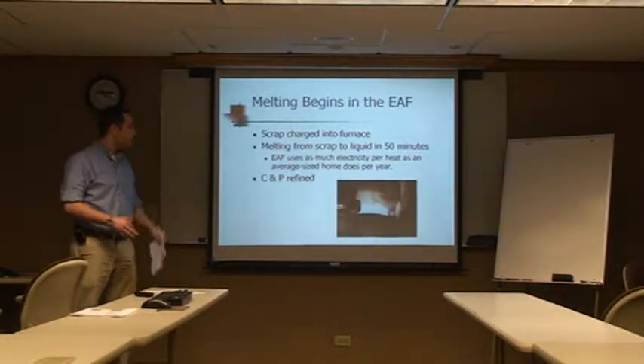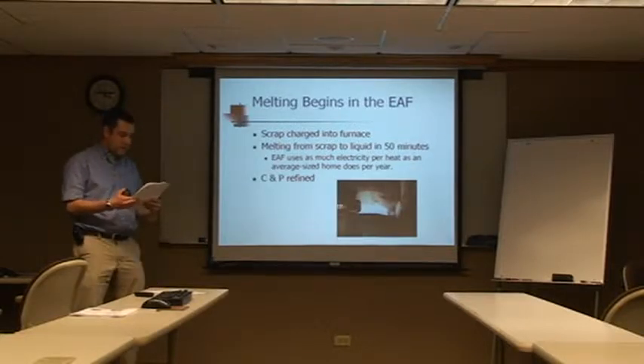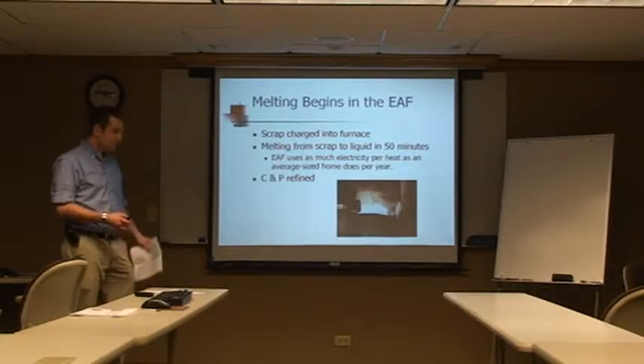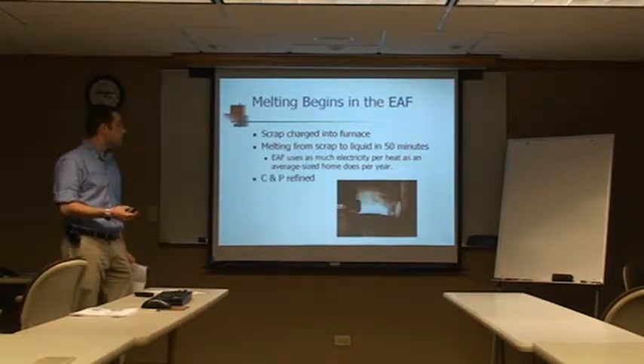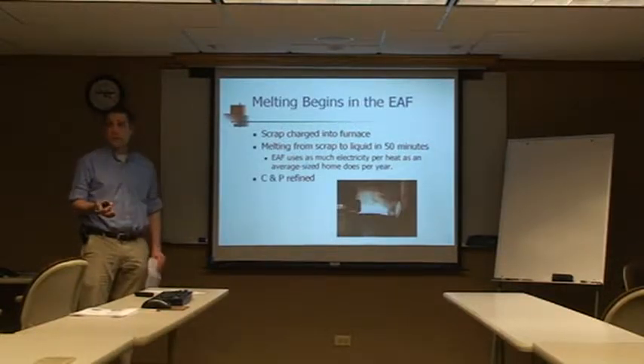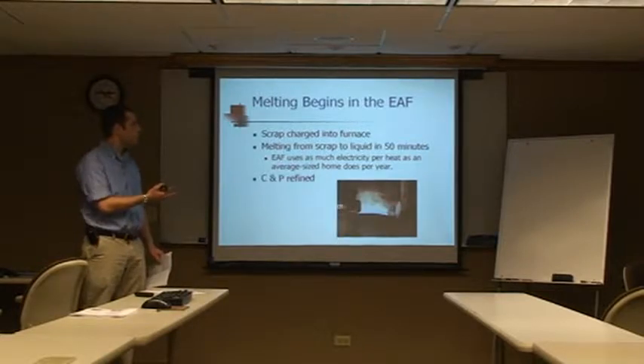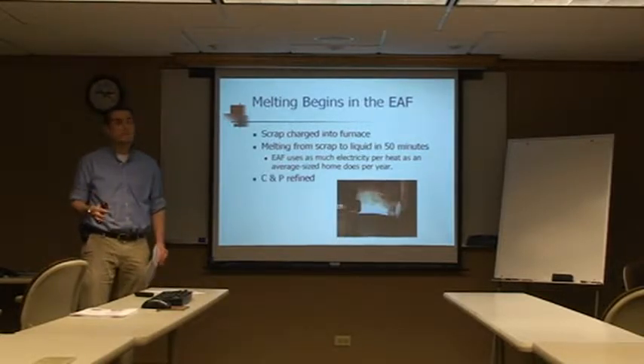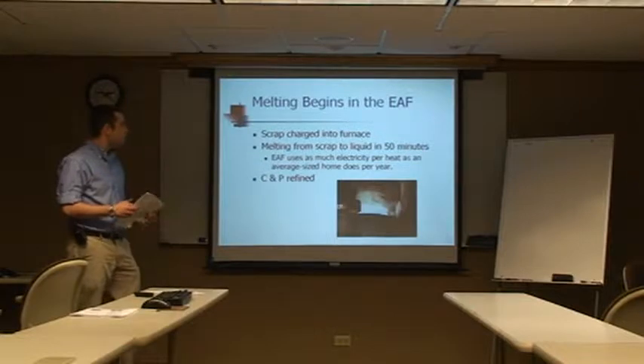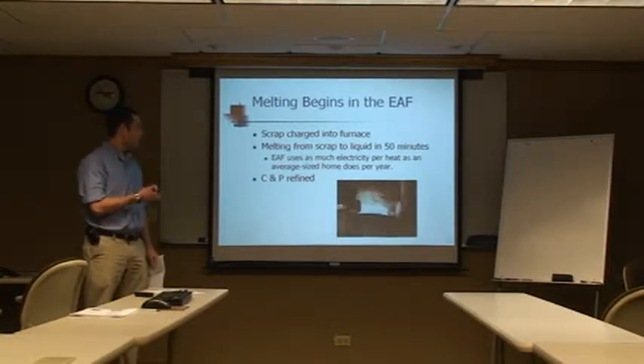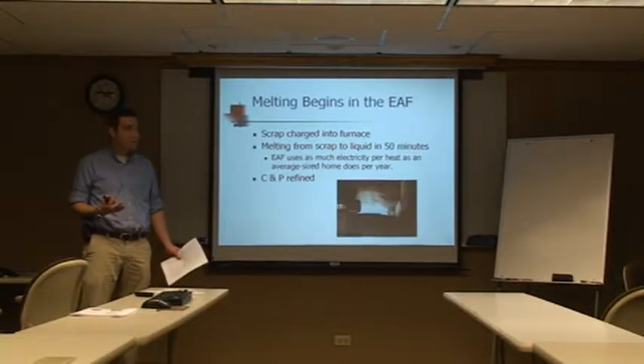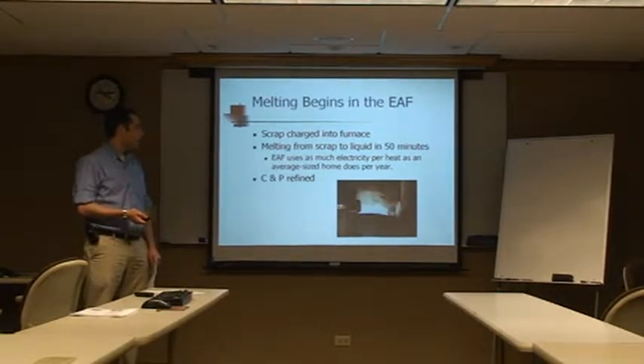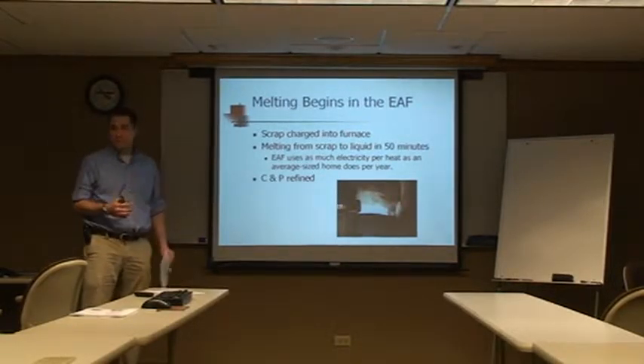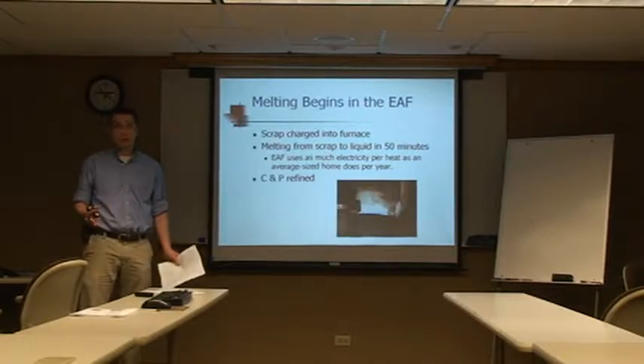So when the steel making process begins, the scrap material is collected into charge buckets and placed into the furnace. The melting of a heat, which starts from pure scrap, normally takes about 50 minutes. And as I've also noted on the slide here, the electric arc furnace is an electricity hog. It uses as much electricity per heat, which again is about 50 minutes, as an average size home would, one that has electric heating and air conditioning for an entire year.